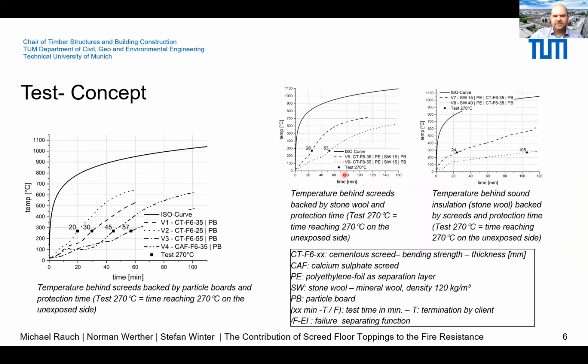The diagram on the left side shows the result of test 1 until test 4. For the protection time, the temperature of 270 degrees is evaluated and shown in the diagram for the different screeds and different thicknesses backed by a particle board. Tests 1, 2, and 3 were done with a cementitious screed, and test 4 with a calcium sulfate screed.